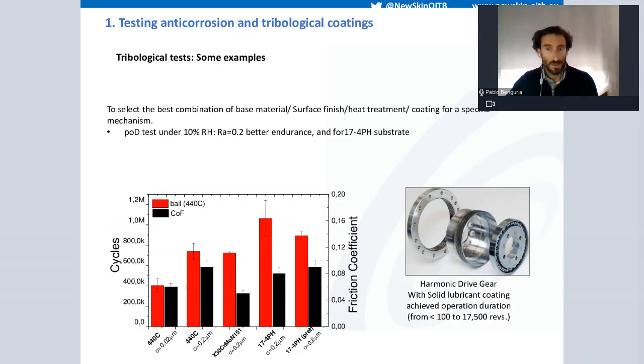In the next slide, I will show you very briefly an example of a selection of substrates that we performed in a private project. We had a given surface coating that has to work in a harmonic drive gear for the aeronautic industry, and they wanted to select which steel substrate would withstand better the conditions during working. So we selected the best conditions, and we achieved an improvement from hundreds of operations to more than 17,000 operations. That's pretty much by applying the lubricant and selecting the best substrate.